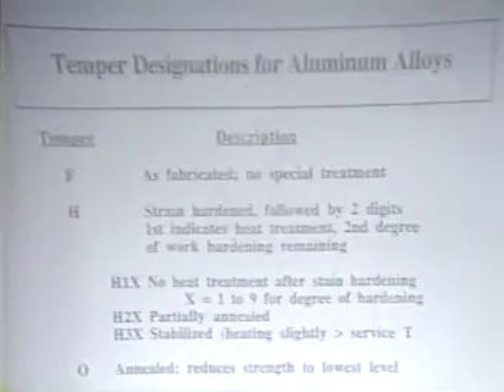Okay? So this is a designation system for wrought and cast aluminum alloys. Now, the aluminum alloy that we use for a beverage can is alloy 3003, and it starts out in the annealed condition. And when I said it starts out in the annealed condition, one way that we control properties in alloys is by chemical or mechanical or heat treatments. And that's what these temper designations mean.